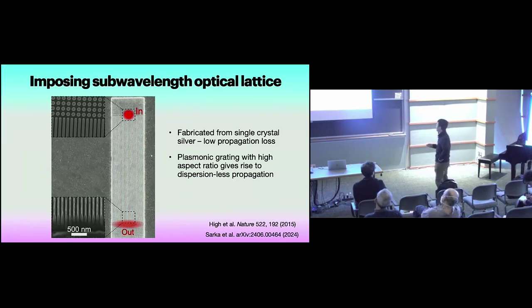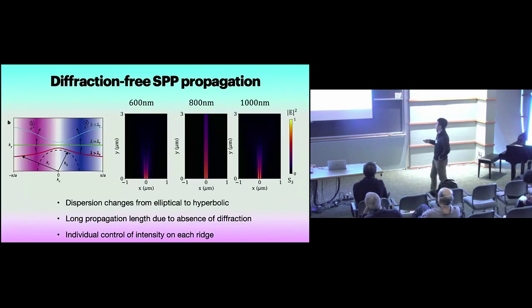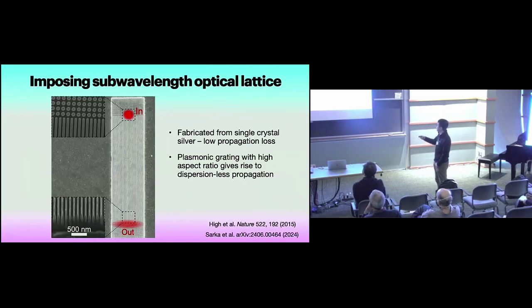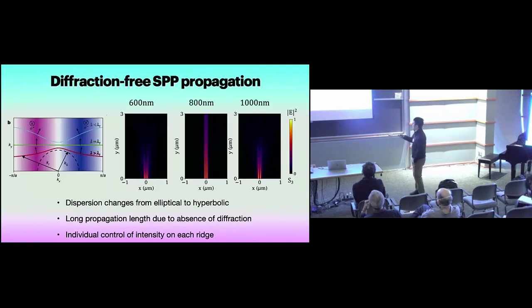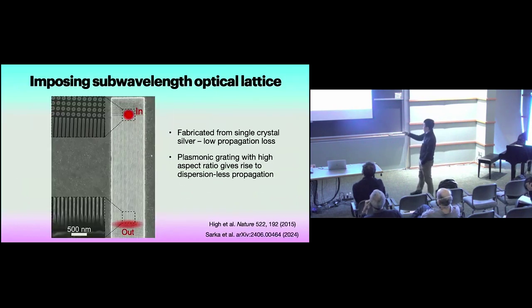absence of boundaries. And also, this type of structure allows you to realize very interesting dispersionless propagation. So this is very similar to what Vinod did for these hyperbolic materials, and also Dmitry Basov talked about in these natural polaritons. Because these are highly anisotropic along this direction versus this direction, right? So the property is very different. Along this direction, you are just seeing the gratings. Along this direction, you see air and the air grating repeating itself.